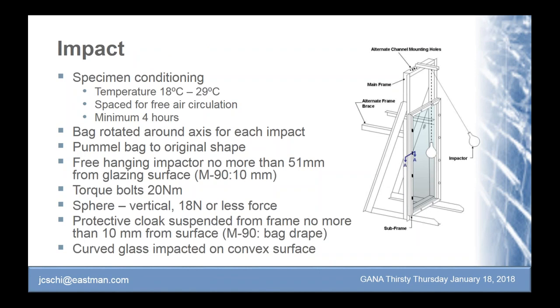The impact is also the same. There is a temperature conditioning requirement that wasn't there before. It specifically says the bag needs to be rotated in between each impact. You have to pummel the bag to the original shape prior to testing, and it could happen to need to be pummeled into shape with a mallet in between each test if it's a very hard material and the bag does deform. And then all the rest of the information is essentially the same. So there isn't a change to having to get new test equipment or anything like that.